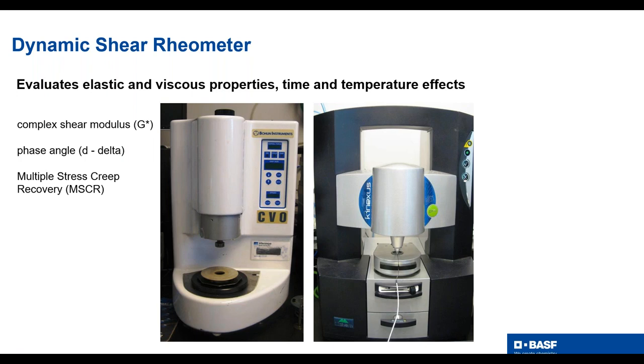One thing I wanted to mention, the dynamic shear rheometer: there have been a couple of agencies that have spec'd DSR measurements on some microsurfacing residue, and I think you'll start seeing the DSR being used more and more. But when we really want to identify a lot of performance related aspects of microsurfacing, not just use a DSR as an expensive purchase spec, because it can obviously replace a softening point or a penetration, but it's an expensive alternative. If there are tests that can really show performance aspects of microsurfacing, that can give agencies the opportunity to use it more and more confidently. I think using the low temperature recovery residues in a DSR will come to a lot of fruition in the near future if the performance can really be seen. So I wanted to show the picture of the DSR just to show that it can be used, and I think it is a future test to be used.